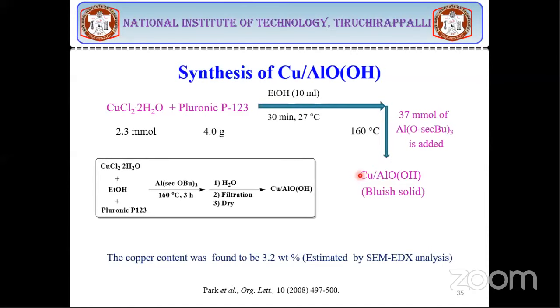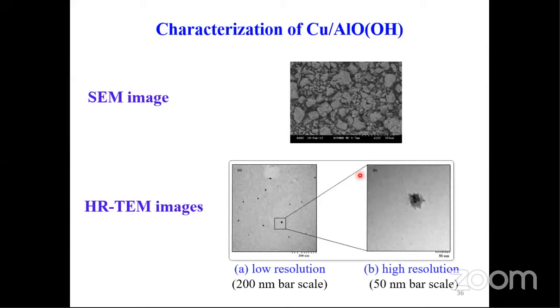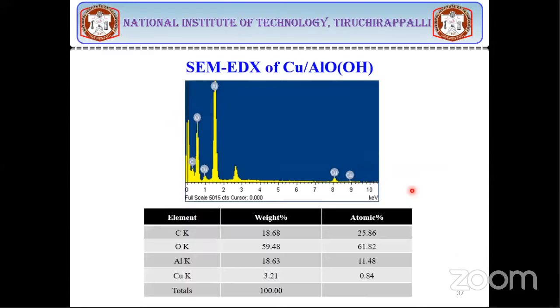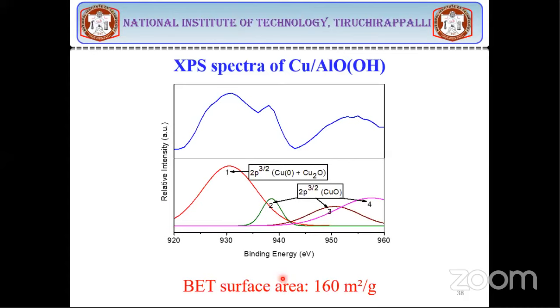And this copper on boehmite, I just show the characterization and then I go to the importance. And you just see here, there is a formation of copper clusters on the surface of the boehmite, and the amount of copper is found to be 3.21 weight percentage. And just to see whether there is only metallic copper, or also we have copper oxide on the surface of boehmite, we have performed XPS analysis, and you can see here, in addition to metallic copper, a trace amount of copper(I) and copper(II) oxides were also present. And it is obvious that when copper is exposed, it will immediately form copper oxide. So the stability is not very excellent. At the same time, the stability is enough to carry out the reactions, right? And if you want to keep the catalyst for a long time, you have to store it in an inert atmosphere, right?